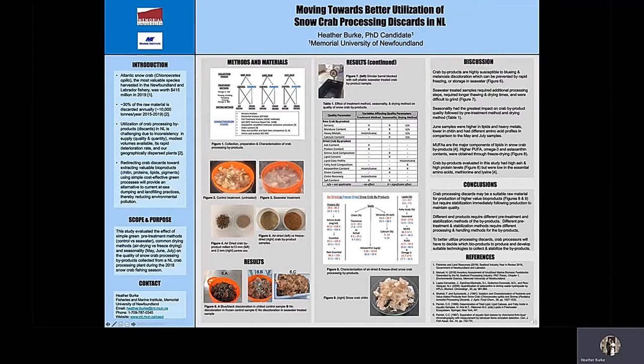The collection pre-treatment methods affected the quality and the handling requirements of crab processing byproducts, as shown in figures 6 and 7. Treatment with seawater was effective in preventing the blue-black discoloration that was observed in the control samples. However, the seawater-treated samples became very pliable and were more difficult to process. The drying method had a major effect on fatty acid composition and astaxanthin content, with higher polyunsaturated fatty acids, omega-3, and astaxanthin contents obtained through freeze drying.